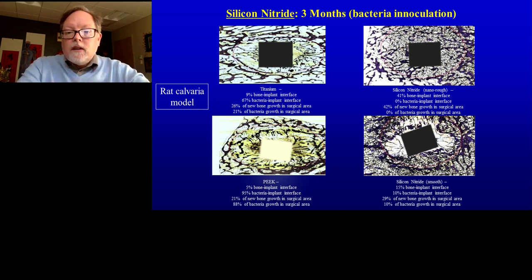Again, each of these micrographs are histology stains in which we had the implant with bacteria on it and inserted that into the skulls of rats. On all four of these images, if you see yellow, that means an infection. That's a stain for bacteria and biofilm-producing bacteria. We also have a stain for bone growth, and that's purple. So if we look at the worst material, again, PEEK, that I mentioned in the lower left corner of this slide, there was a ton of infection.